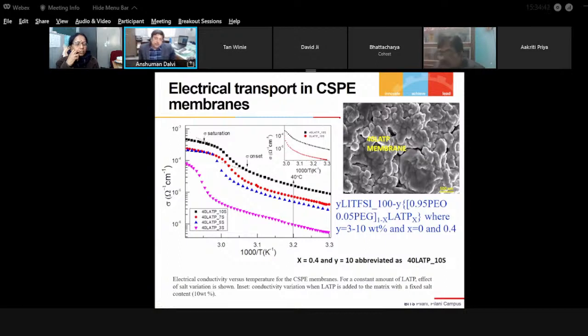Now, regarding the electrical transport, the films initially used for the fabrication of supercapacitors did not have very high ionic conductivity. This moderate conductivity of between 10 to the power -4 and -5 was used initially to see the effect, because initially we have to go with the lower things, and later on we can look for a better ionically conducting system and optimize. So with lesser ionic conductivity we initiated the work. Here this is the LiTFSI salt and polymer with a little amount of PEG, and this LATP, the lithium NASICON structured lithium ion conductor, was dispersed inside with 30 to 40 nanometers size.